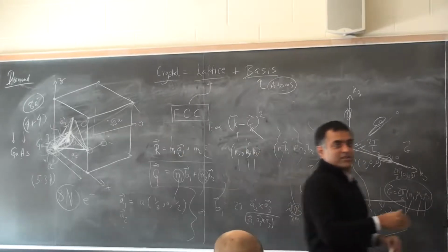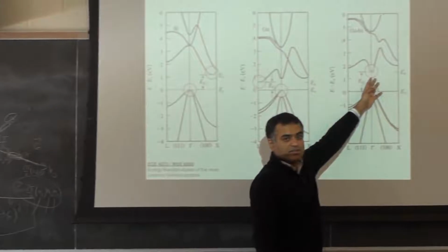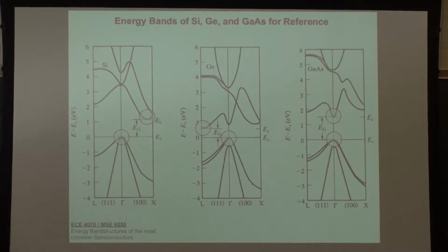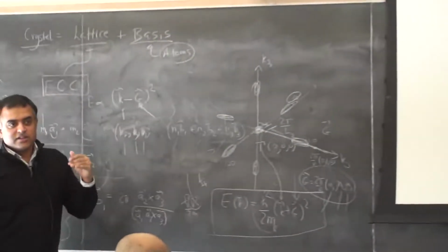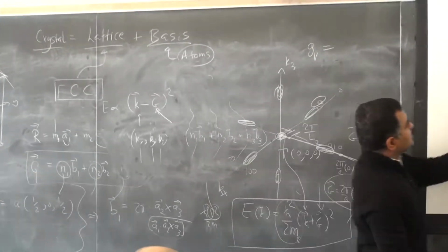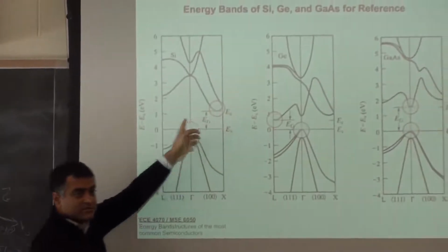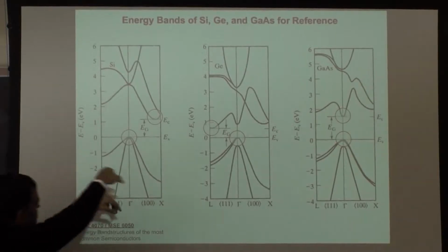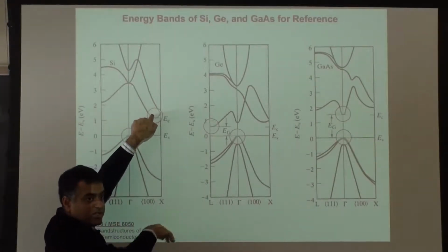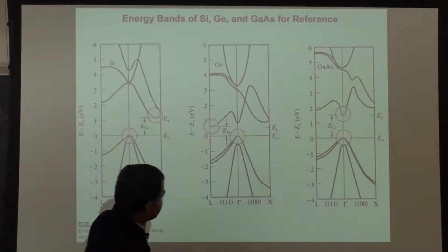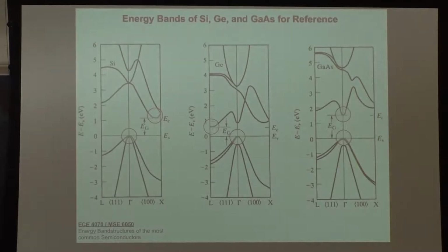And what about gallium arsenide? How many minima? Just one. It's at the gamma point. It has no degeneracy. There's only one such point. So the valley degeneracy of silicon is 6 for the conduction band. That's what we mean. It's a valley in the energy space, the minimum, and there are 6 of them. The valley degeneracy of germanium is actually 8, but it turns out that it's shared between the next zones, half of it lies inside, and it's actually 4.